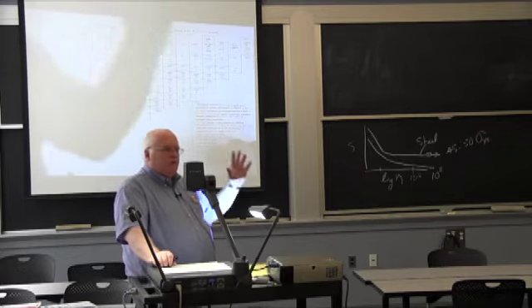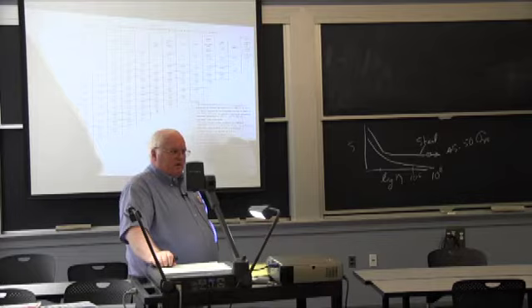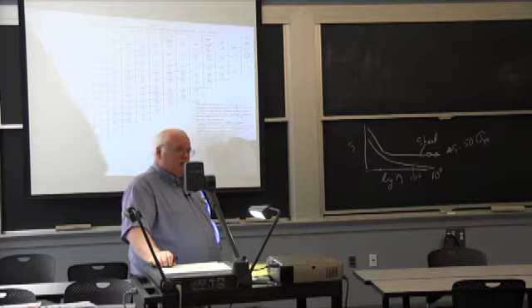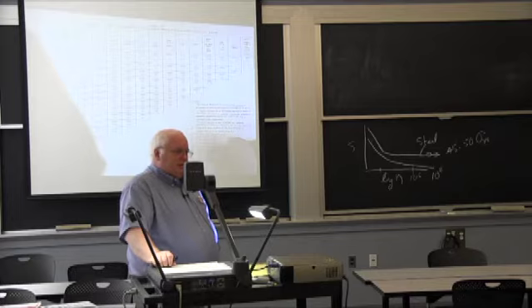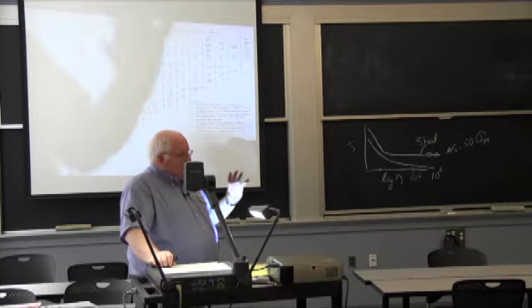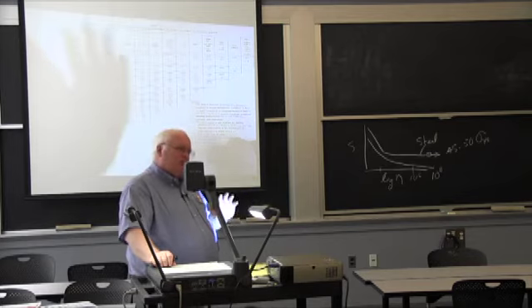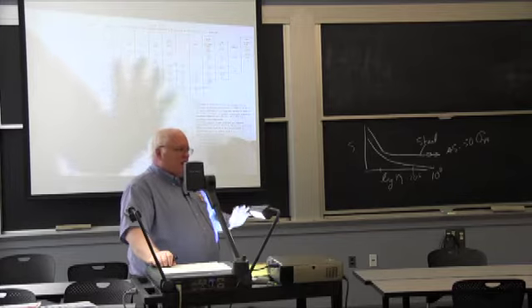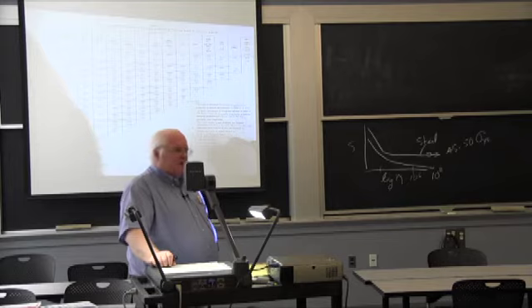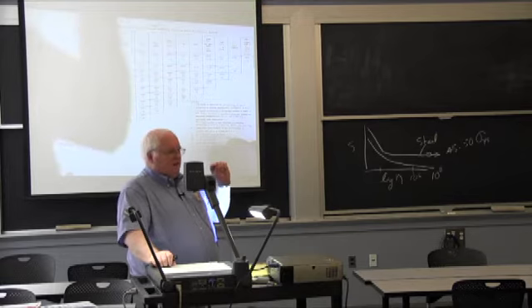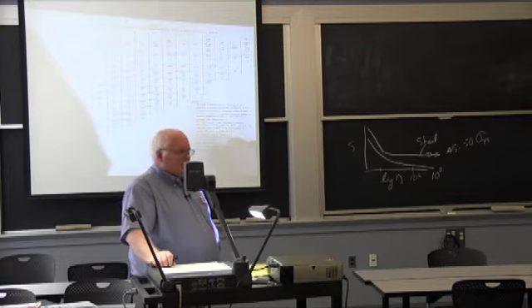You can hear about wonderful aluminum alloys with tremendous strength. Anybody have an idea what the highest technology strength for aluminum alloys is? You can get aluminum alloys close to 100 KSI yield. What's the application? Baseball bats. Okay? Turns out they slim them down and they slim them down, and they have special alloys used only for baseball bats, and they heat them up and they quench them in ice water in order to maintain fine grain size, and they will get higher strengths than anything used in any aircraft. Okay? But they're very thin. They're about 20 thousandths thick at some spots.